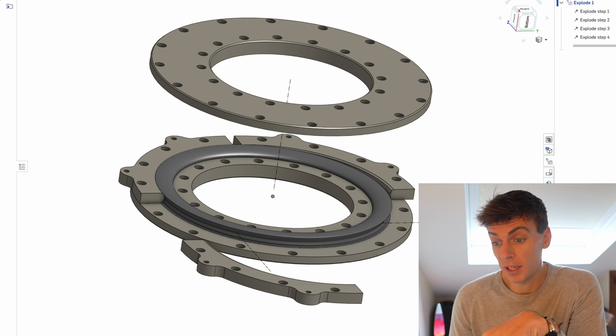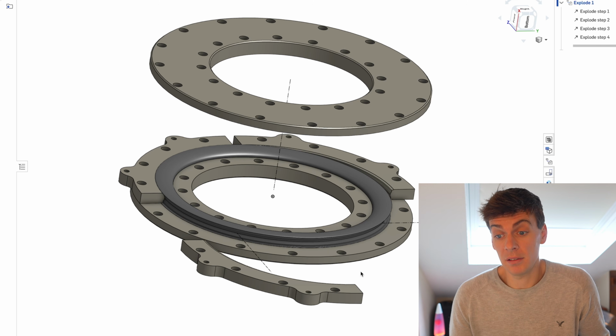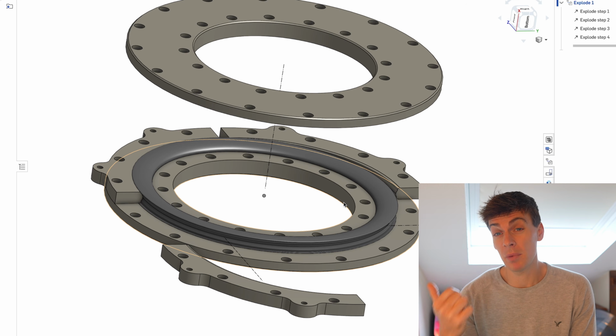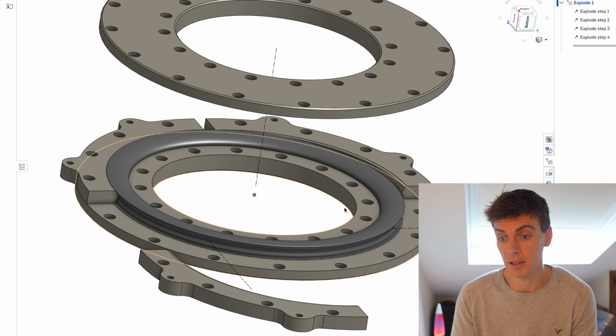You lift the top off and you take the center portions out, maybe 4, maybe 5, maybe even 3 if you can do it in 3. Pull those out and then you're finished. Your rim comes out. So it's a lot simpler to manufacture. The tolerance stack up is lower, and because there's way less parting lines, like I said, there's more a chance that your volume fraction of fibers to resin ratio is going to end being correct because you haven't got so much resin flowing down the parting lines.